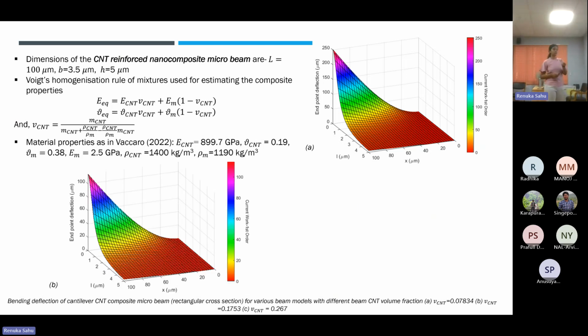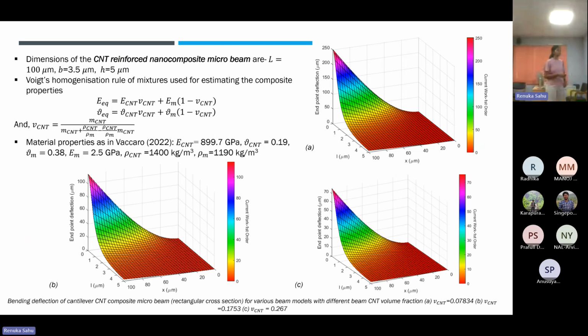This is done for three different volume fractions of the CNT, as given. When we increase the volume fraction, the stiffness of the beam increases, and combined with the strain gradient theory, this gives a much more stiffened beam.